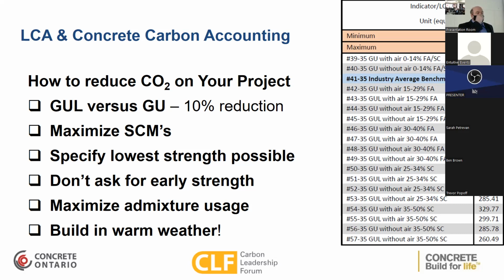Maximizing the use of supplementary cementing materials like slag and fly ash or other innovative new products. Again, we've been pushing those for 20, 30 years because they also have the added benefit of increasing the concrete performance and durability. So there's a double benefit when it comes to pushing things like supplementary cementing materials. We get higher strengths, lower permeabilities, and lower carbon footprints because they have a lower carbon intensity. So again, we're seeing a lot of press for that.